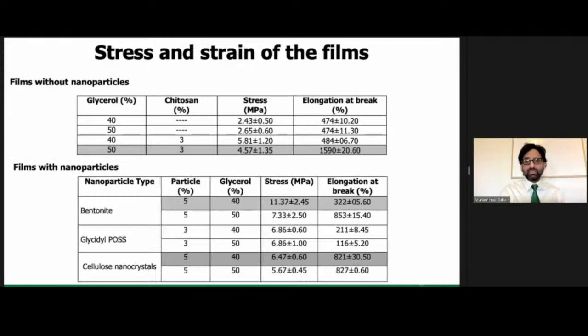And these are the films with nanoparticles. The first one is the bentonite, then Glycidyl POSS, and the cellulose nanocrystals. As we can see, the stress or the mechanical strength of the film was 2.43, which was increased up to 11.37 by the addition of the nanoparticle, that is bentonite.